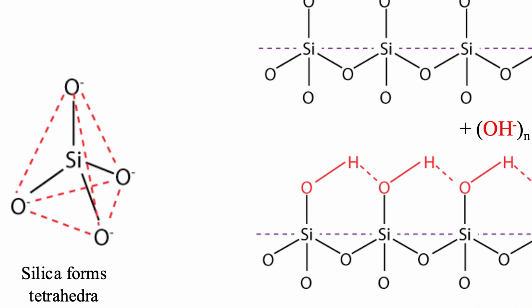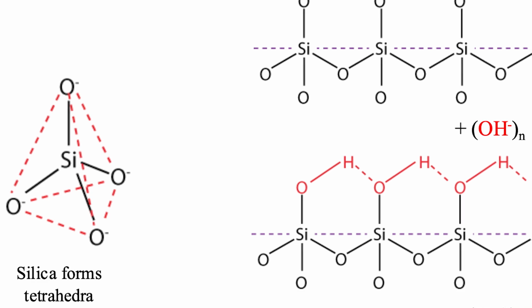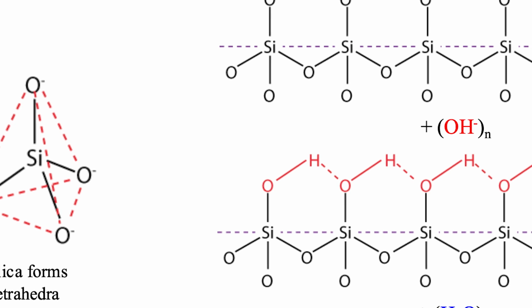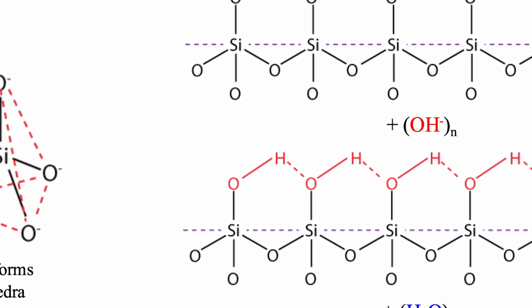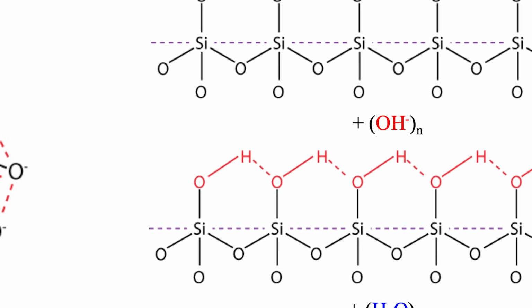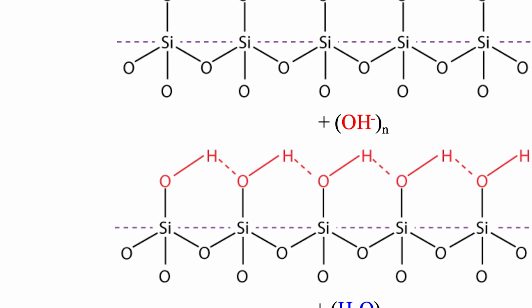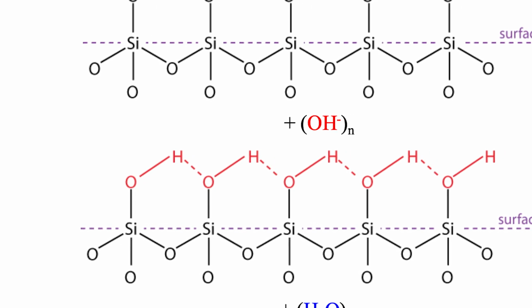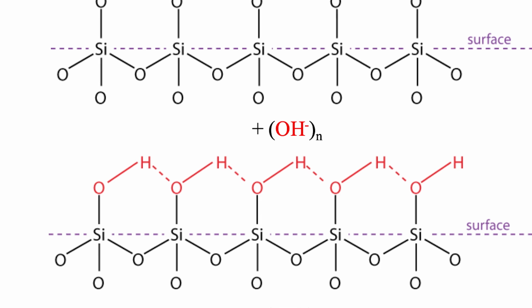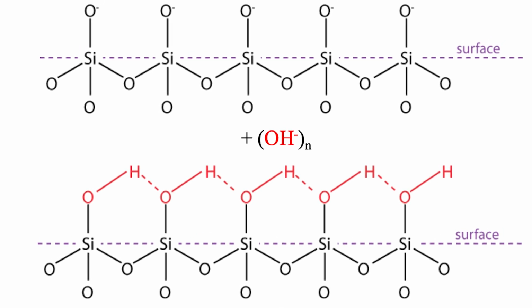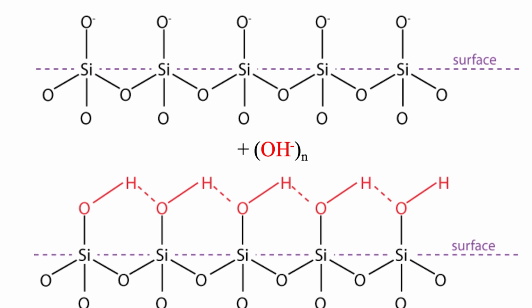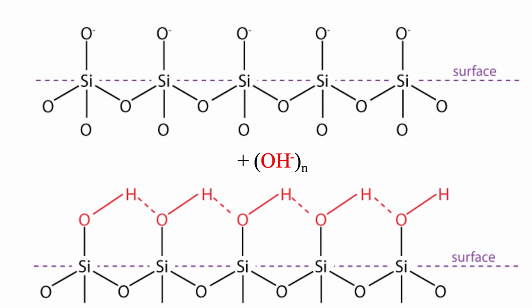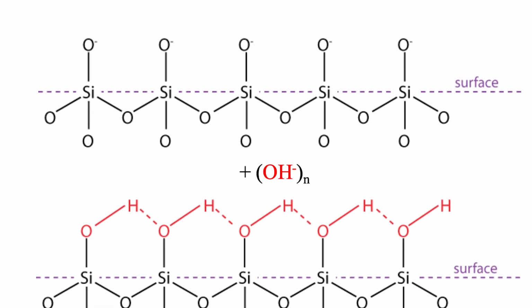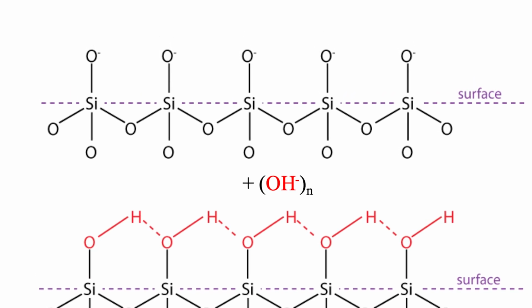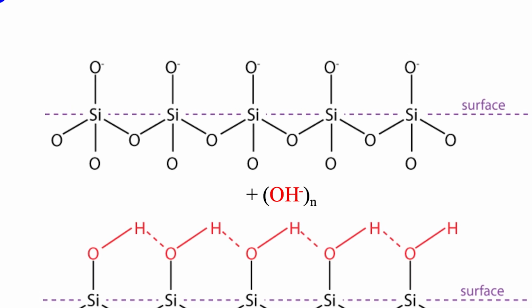But where is this water located? Well, the raw structure of silica, SiO2, forms these little tetrahedral structures. These link up together through here. So each of these oxygens shares another oxygen either side of it. And in the normal flint, that would leave a free oxygen bond sticking up into space on the edge of the crystal. And oxygen as a free bond doesn't like sticking up in space unoccupied. So what happens is OH groups, if you have a look at the top one first,